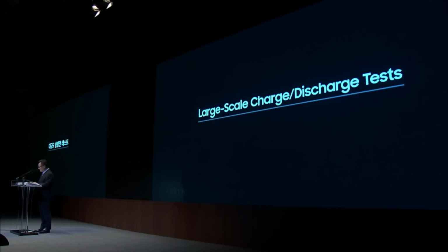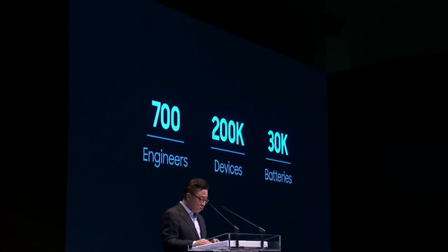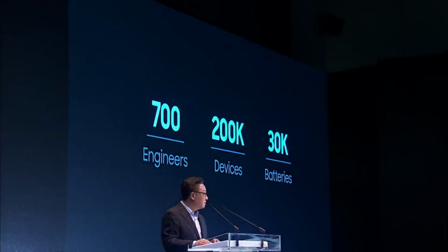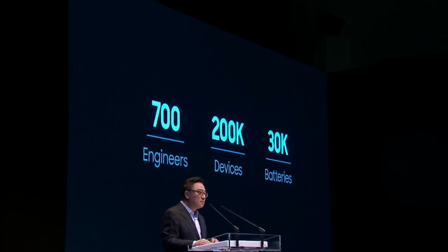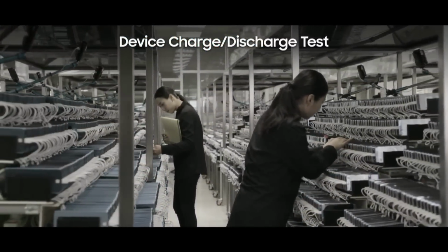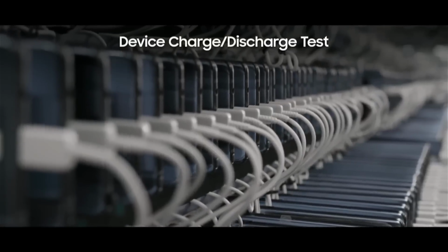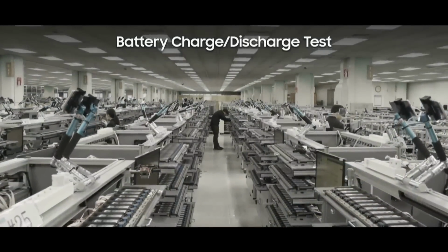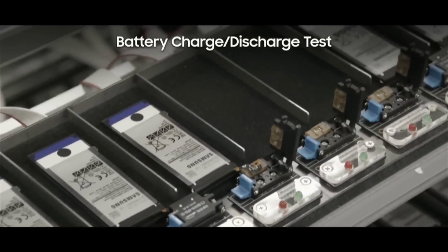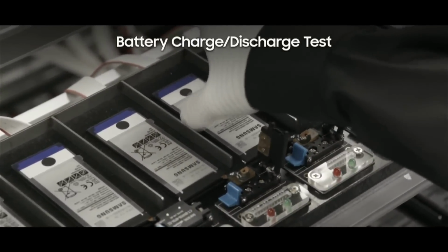In order to replicate the incidents observed in the field, over 700 Samsung researchers and engineers spent several months analyzing more than 200,000 fully assembled Galaxy Note 7 devices, as well as more than 30,000 Galaxy Note 7 batteries. These devices and batteries were subjected to repeated charge and discharge testing. We found that both fully assembled devices and batteries exhibited incidents at similar rates to those in the field. This indicated that the incidents were caused by the battery cell itself and proceeded to focus our investigation on the batteries.